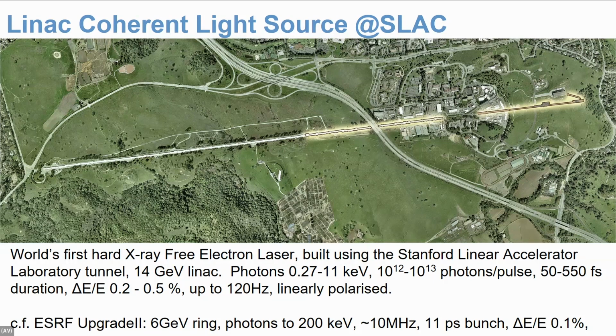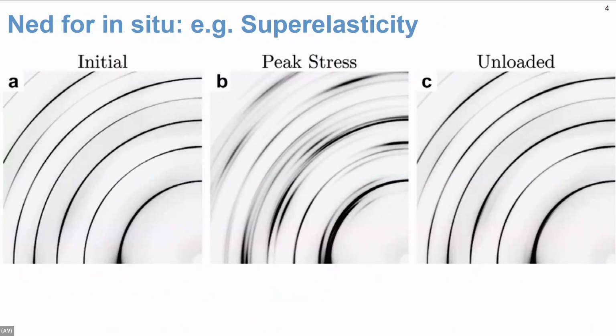So a few years ago, I did a couple of experiments at LCLS, where we started to think about what this would enable us to see that we can't see normally with synchrotrons. Just as an example of why that's interesting, this is a synchrotron experiment from early in my career, where there was a Science paper announcing a new material with some amazing properties and postulating a mechanism by which it derived those properties. And we went and did a synchrotron experiment where we showed that actually it was conventional superelasticity due to a phase transformation that was stress induced.